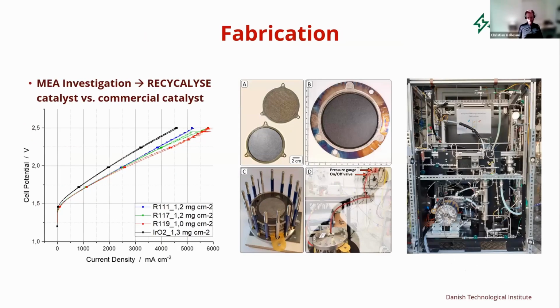So how do we make sure that this boosted activity is also reflected in the MEA, and then how can we decrease the amount of catalyst that we use? A lot of work together with our partner Blue World Technologies in Denmark was done on optimizing the amount of ionomer, which ionomer. All sorts of parameters were optimized in the end, coming up with a MEA structure that we integrated in a stack. And then the stack was tested in the system you see here to the right, down in Austria with our partner Hysenta.